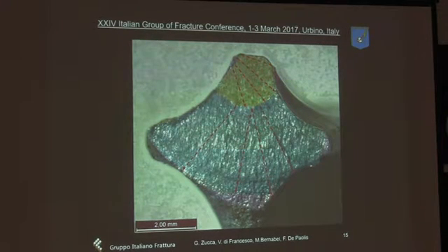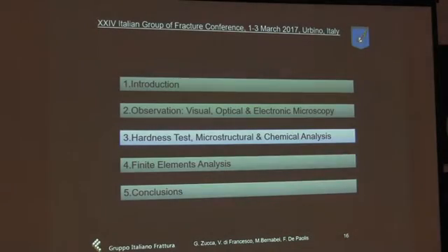So what we can say at the end of the observation is that the crack originated probably from this side, propagated firstly from your left to your right with a path of 45 degrees more or less, and then acted as a second initiation track for a second propagation, with a continuous change of path, but macroscopically we have a second propagation very symmetrically on the fracture surface.